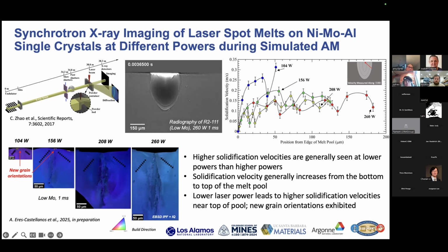The way this works is you have an X-ray beam that comes in, you've got the location of your sample, which can be a thin film, a film with powder on top, or just a packed powder layer. The laser beam comes in, impinges on the sample, and you can create a molten metal pool, a spot melt or a raster, and you can be optimized for imaging or diffraction. But this is a nice example of one of these spot melts of a single crystal, and you can see the sloshing of the liquid in the melt pool. And importantly, we can now also track the solid liquid interface, or the velocity.